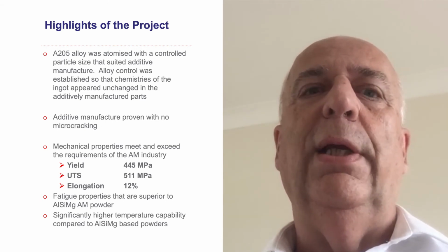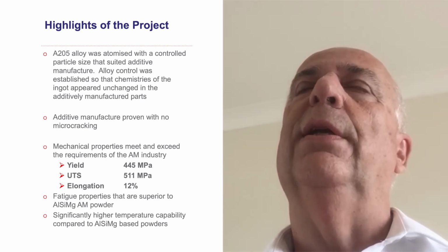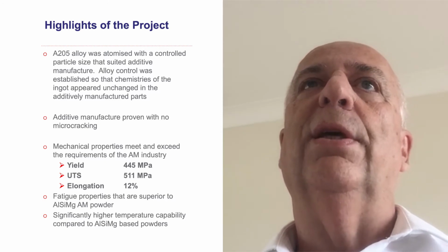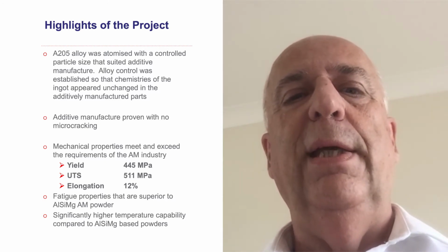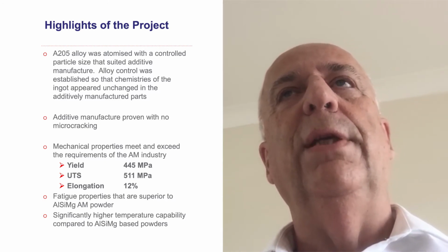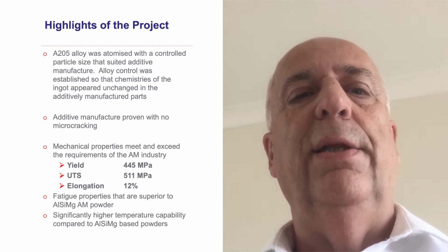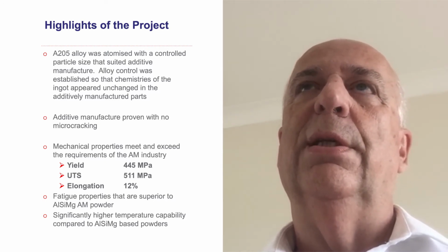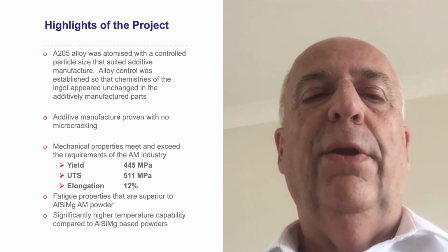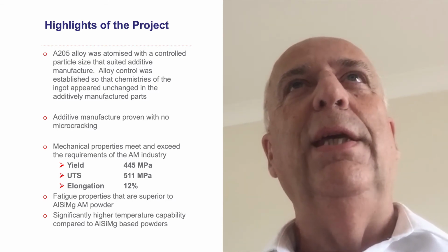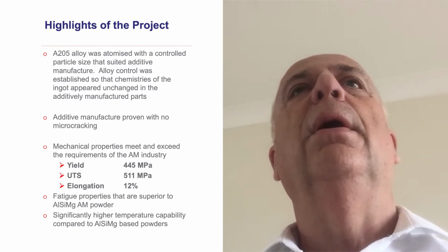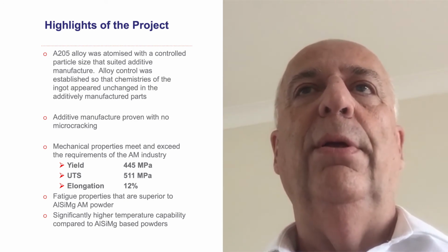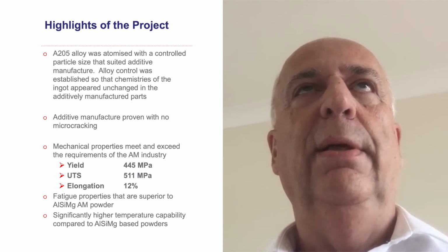And very importantly, it had high ductility at 12%. When you compare that to the cast material from which it was made, you'd have ductility of 3 to 5%, and the elongation was 12%, so you can see it's significantly better. Those mechanical properties make it equal to any other high-strength aluminium powder that's on the market at the present time.